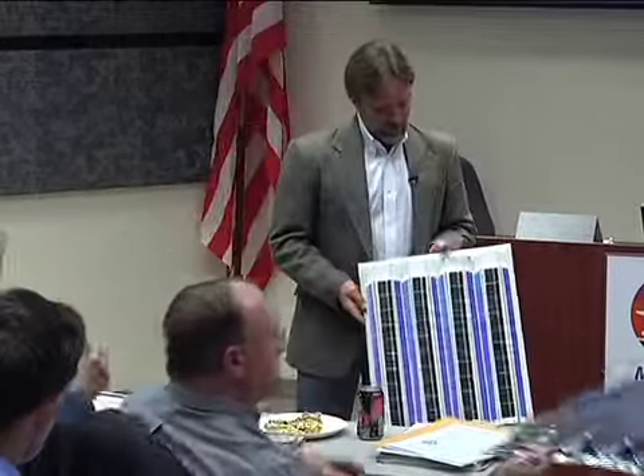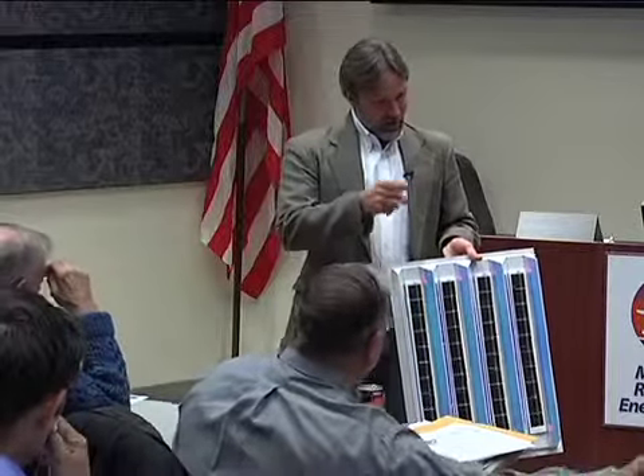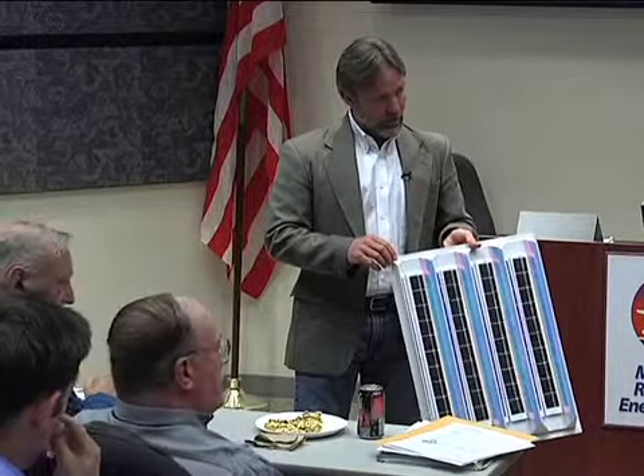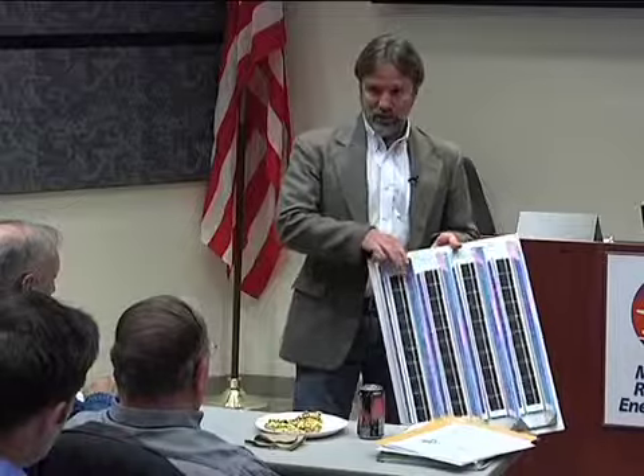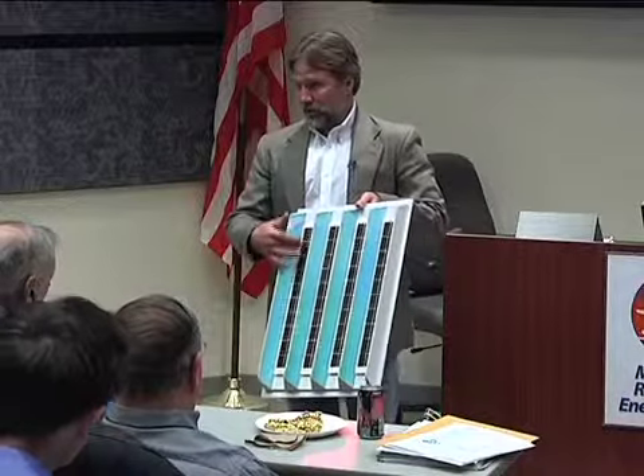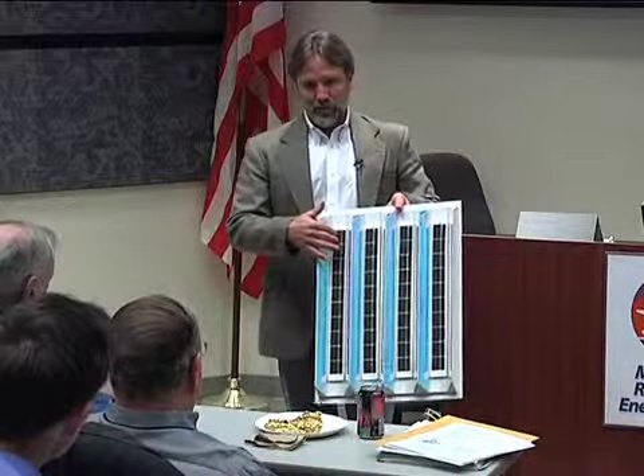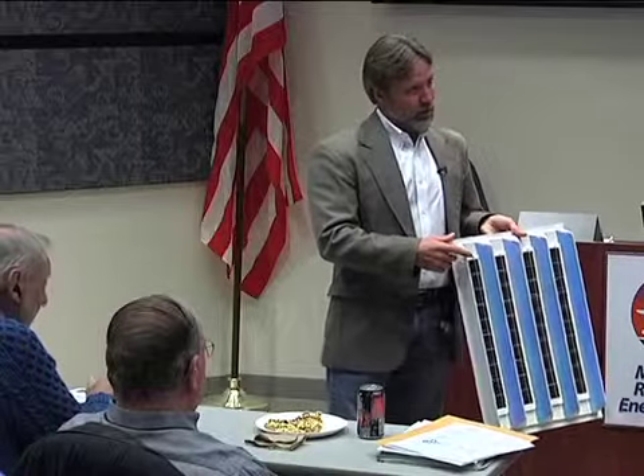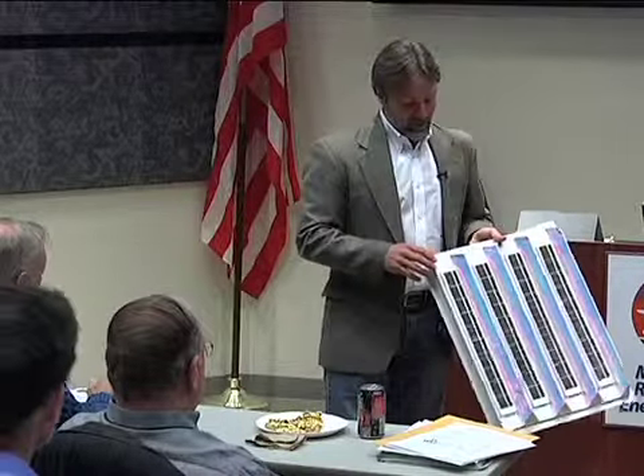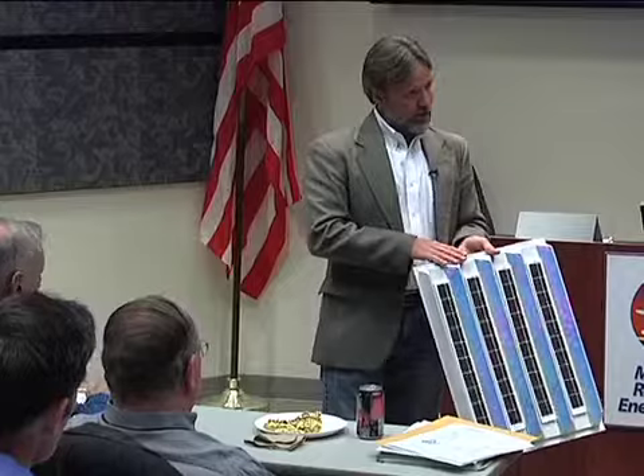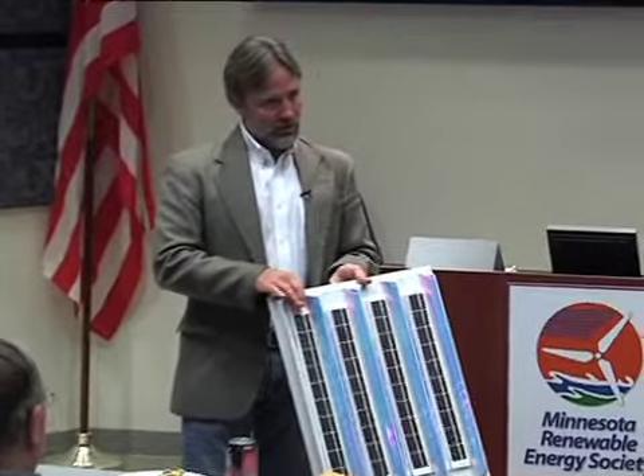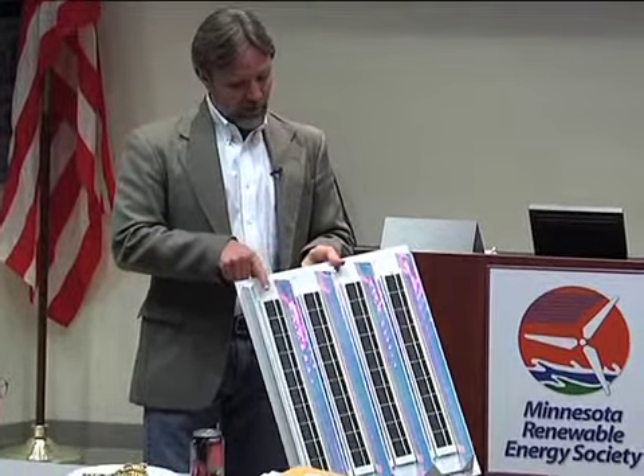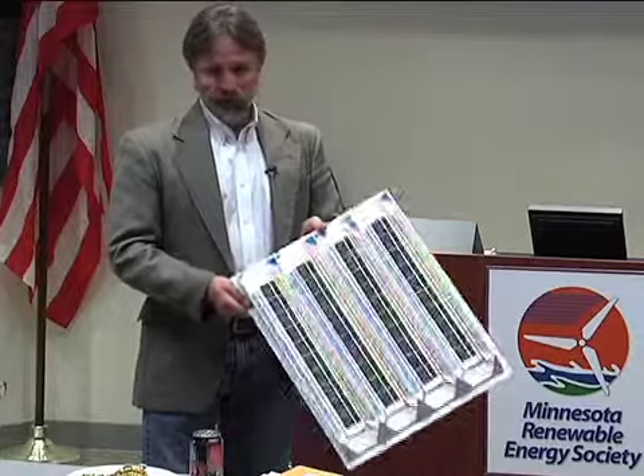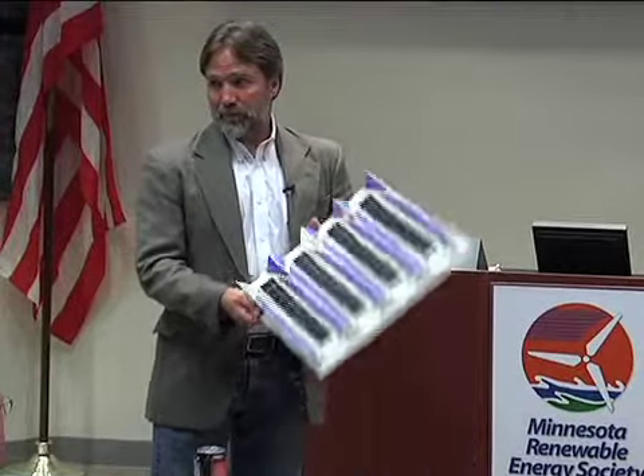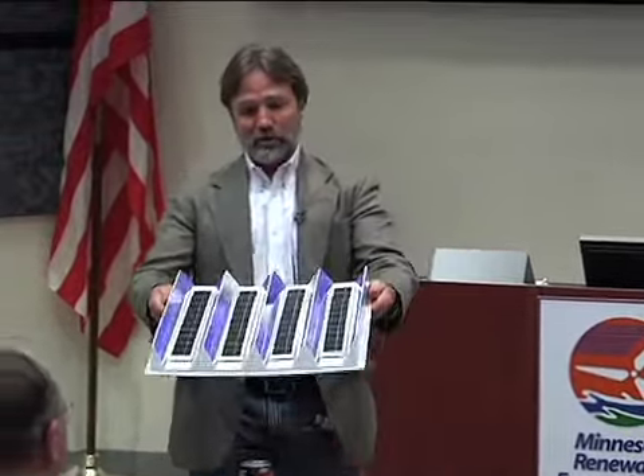And the real value here is that the polymeric mirror film is about 1/10 the cost of the photovoltaic cell. So you have photovoltaic cells here that are roughly $200 a square meter, and this mirror film is about $20 a square meter, roughly. And so you can make a module with half as many cells, by replacing half the cells with mirror films, and drop the cost by 30 to 50%, depending on how efficiently you do it.